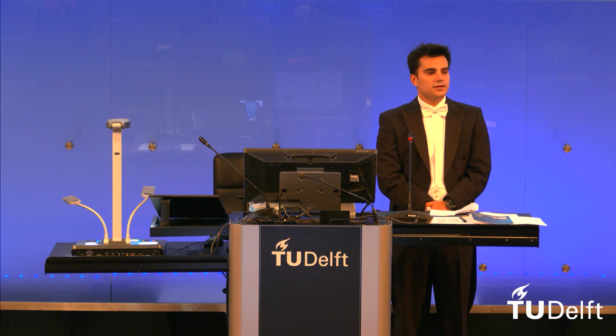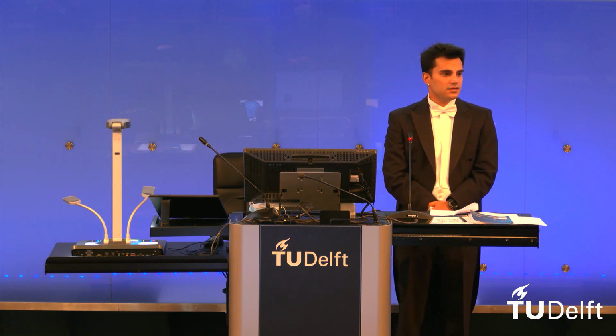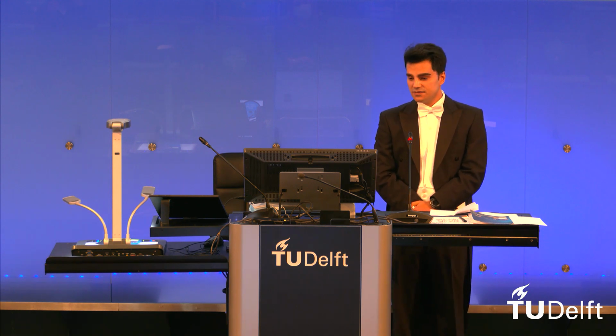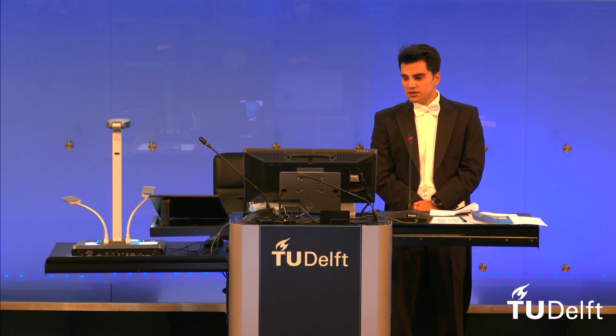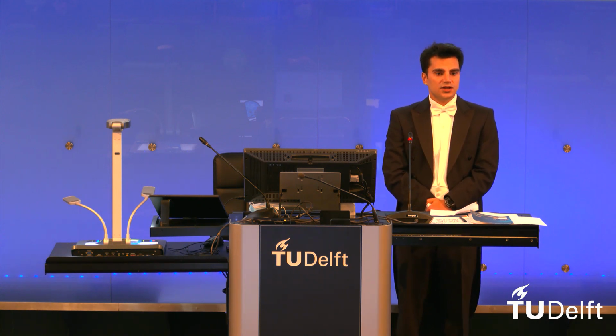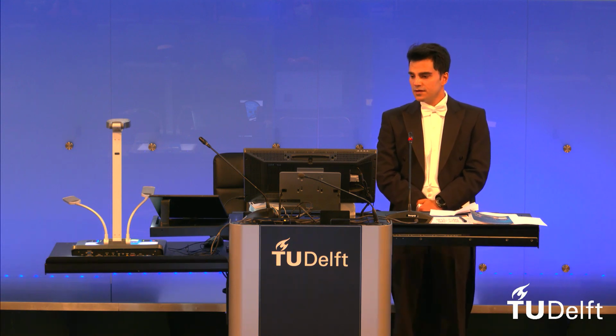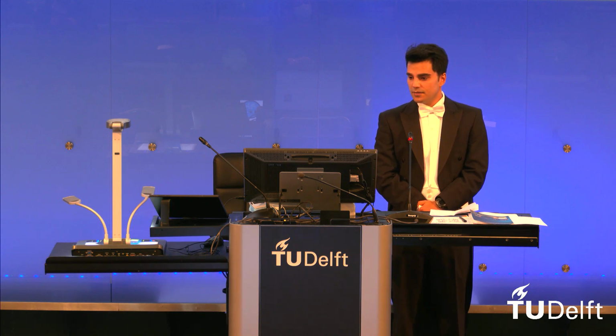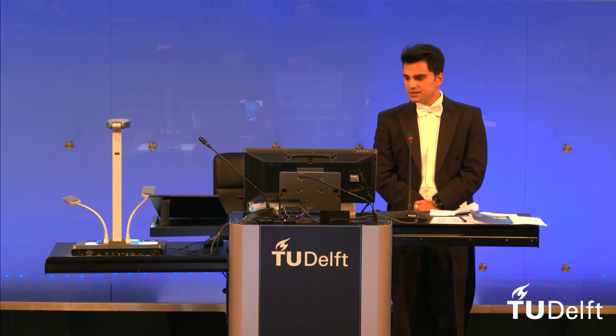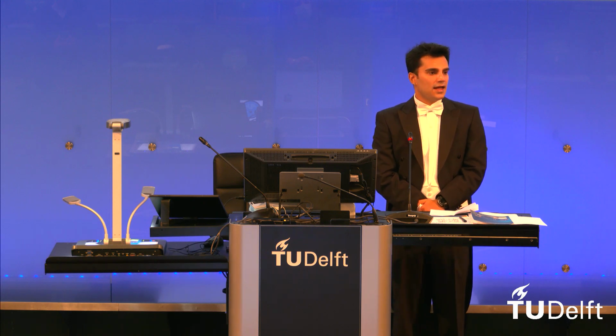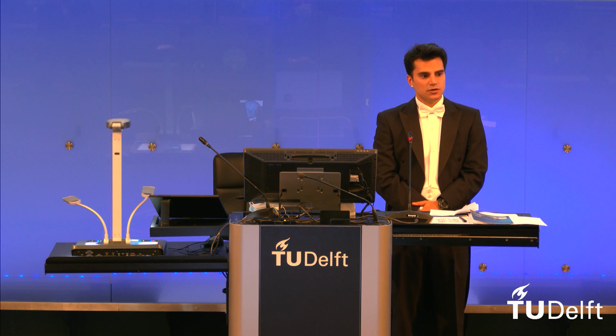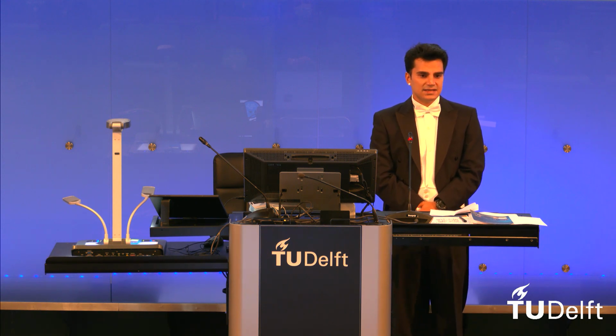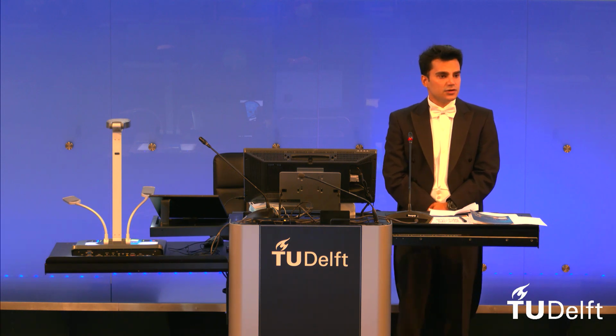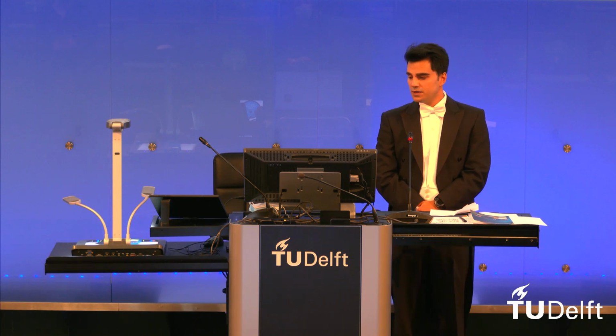And here we have some conclusions on this chapter. As you see, CT could accurately reconstruct the RCF cracks below the rail surface. We compared the CT experiments with the microstructural observations, based on which we could confirm that this method can be validated through metallographical observations. CT is shown to be a reliable technology for analyzing young squats. The next conclusion: the quality of CT measurements and the CT settings have been investigated in order to create a kind of instruction for future users who are going to use CT scan for this purpose. So they can use it as a recommendation to know what the samples should be and what the device settings would be.